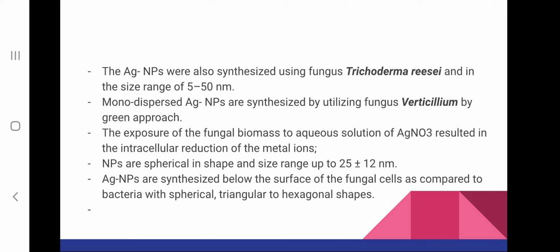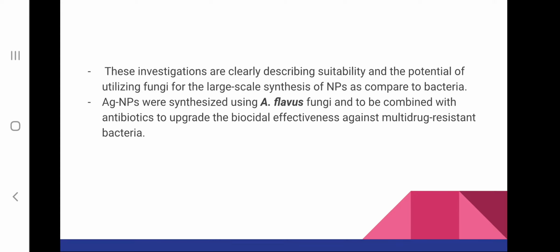And usually in using Verticillium, the fungal biomass is exposed to an aqueous solution of AgNO3, and thereby spherical-shaped nanoparticles of 25 plus or minus 12 nanometers are synthesized. They are usually synthesized below the surface of the fungus cells, and they have different shapes like spherical, triangular or hexagonal. Next, Aspergillus flavus can also be used for synthesizing nanoparticles.